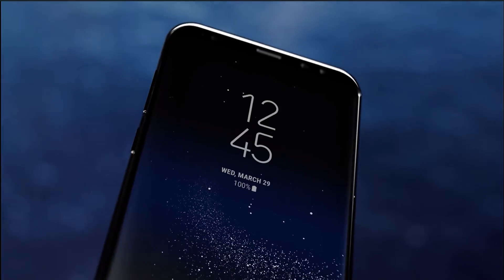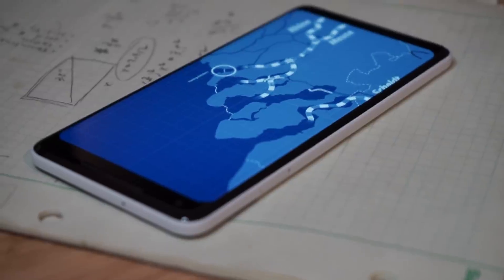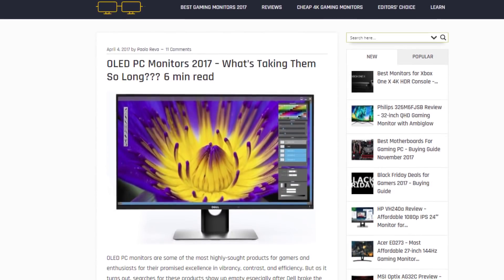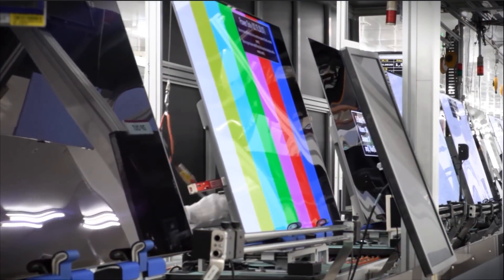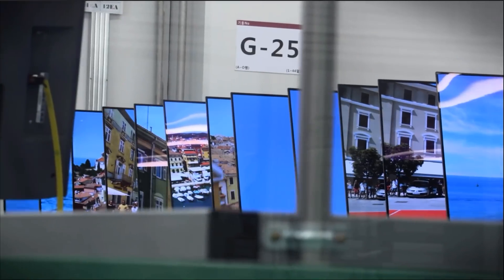There are some growing pains with OLED technology holding it back in the mainstream consumer market. The chief limiting factor is burn-in, which occurs when the organic layers of the pixel begin to break down from prolonged usage. As the layers decay, they become significantly less bright than the pixels around them, which can make stationary UI elements appear as ghost images. This mainly occurs from prolonged static images, such as user interface icons, and is the single largest reason OLED computer monitors or TVs are not yet mainstream. Not to mention the cost, which can be 1.5 to 2 times higher than an equivalent LCD panel.